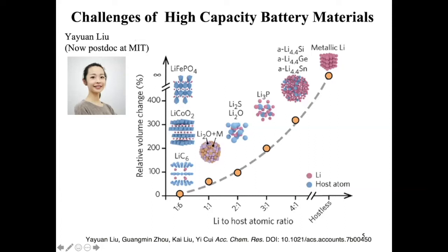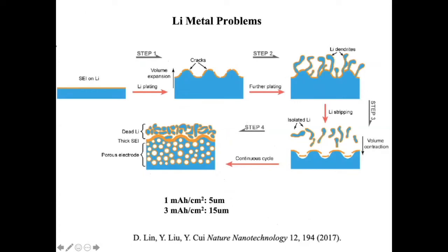So the material design thinking needs to change because of this dramatic change. I only want to focus on lithium metal in this talk due to limited time. Lithium metal, of course, is well known for its problem, like the plating and stripping problem. You need 3 mAh per centimeter square of capacity or higher. So you are talking about 15 micron of lithium deposition and stripping away 15 micron. I mean, this is a challenge we have never been able to deal with successfully for the batteries.